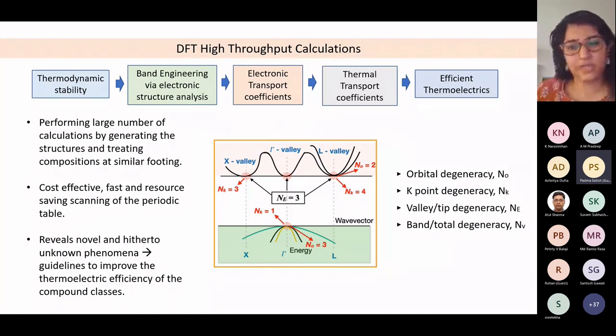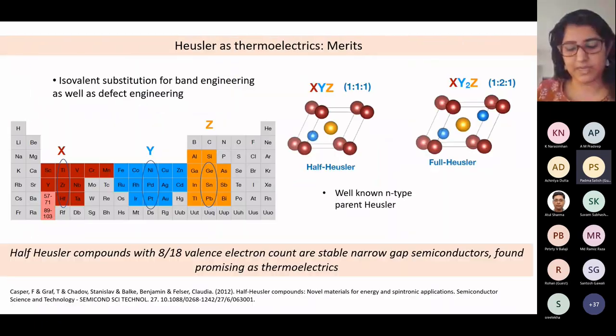Similarly for the p-type situation, I'm not going into the details of this schematic. So keeping one particular case in mind, these are the Heusler materials, and we tried to substitute in this Heusler material, and we wanted to compositionally tune the entire space, starting with 3 different elemental rows in mind. These 3 ideally give an 18 valence electron count half Heusler. It's very stable. So therefore we can look into and find what is the exact compositional space one should look at, if they are going ahead and tailoring the thermoelectric properties.